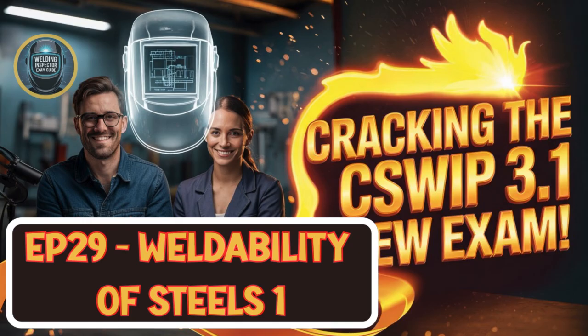Well, if there's one golden rule for hydrogen cracking, it's probably keep it dry and keep it warm. Dry and warm. Okay. So first, reducing hydrogen. This is the most direct approach. It means using low hydrogen consumables like welding rods. Often involves baking electrodes or keeping them in vacuum-sealed packages. Right, like keeping gunpowder dry. Kind of, yeah. For processes like submerged arc welding, or SAW, where you've got that granular flux covering the weld, basic agglomerated fluxes need to be kept in heated silos.